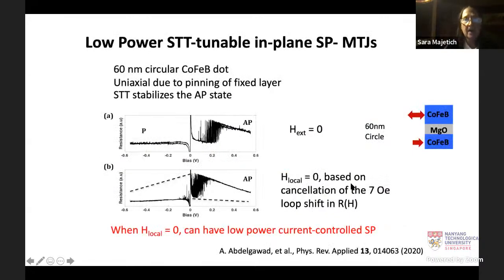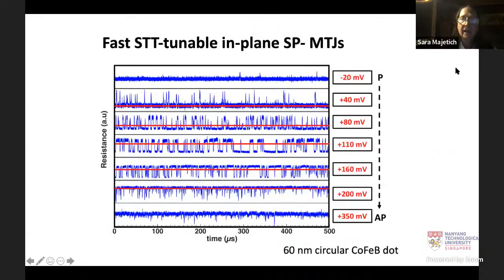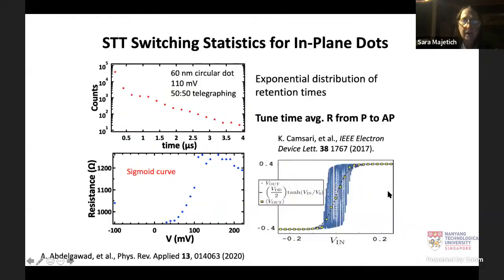And we went to circular dots. And here, we still have a pinning layer, so it's still uniaxial. We still have two levels, but here we can see this get even faster. And if we apply a small local field of about 7 Oersted, we can shift this to cancel the local field, and we can shift this to be around 0. So you really could have low power if you have in-plane magnetization for the devices. And with the low power, we've also been able to get this much faster. We've been able to go down to microseconds and below.